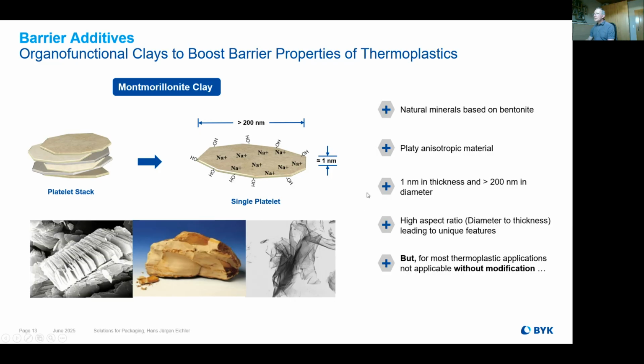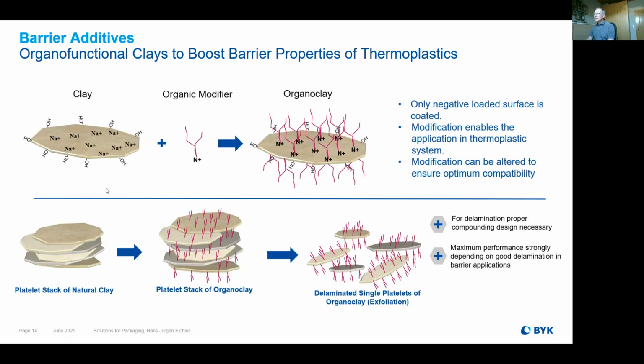To speak about the general things of montmorillonite, as you can see in this picture, it's a very platy, anisotropic material, and the size is very, very small. The thickness of one of these pages is about 1 nanometer, and the diameter is 200 nanometers. That means the material has a huge aspect ratio, which is quite important to get the real performance in the case of the barrier. But the problem is, if we dig it out of the ground and place it into the plastics, we will never have good values, because we need to modify the clay with some organic material.